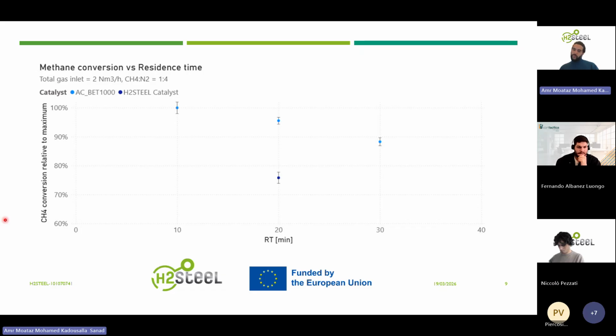Please note that the shown percentages are normalized relative to the highest one and do not represent real percentage points, but rather are used to show how the different operating conditions can influence methane conversion, calculated using the formula shown in the previous slide, of course. The commercial catalyst shows a decreasing conversion trend as the residence time of the catalyst within the reactor is increased. Of course, using the same operating conditions, so the same gas velocity, the same gas inlet and the same reactor level. This is in line with results obtained from lab scale trials and results in literature.